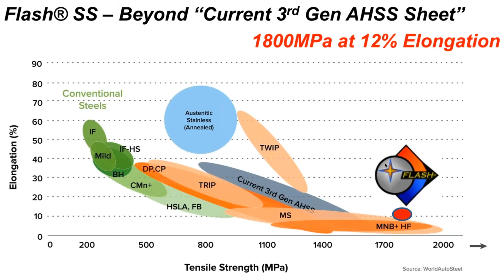And of course, there is an ellipse to the right that's not shown, where they talk about the future third-gen high-strength steels. Well, flash bainite at 1800 megapascals and 12% is up in the range. So I believe it might be fair to say that we've got the world's first future third-gen advanced high-strength steel. We're just waiting to push this into full production once our 10-ton coil-to-coil flash processing line is running at Q2 this year.